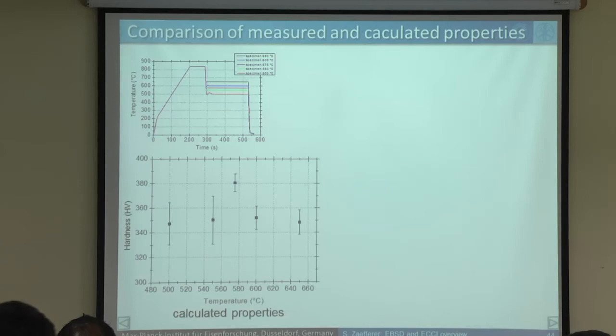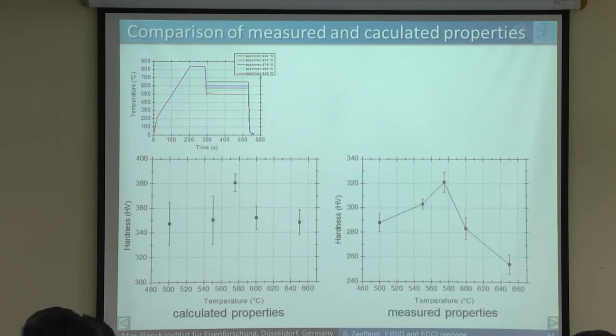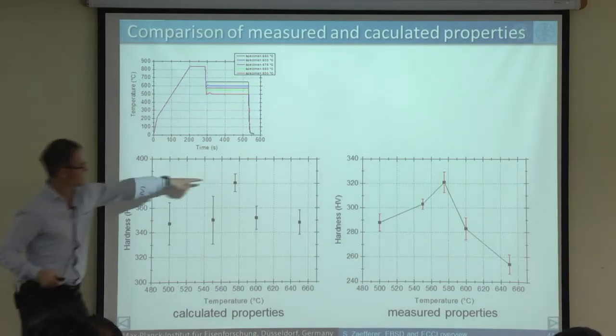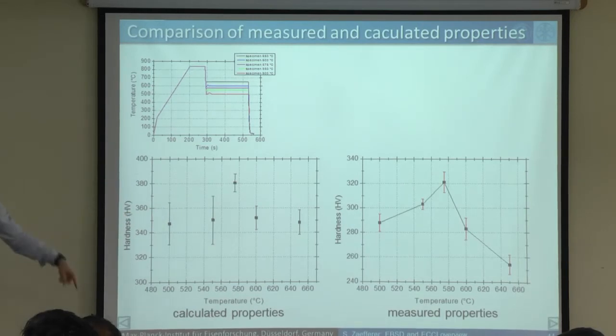And so again, for our experiments, and these are the calculations, and we find out, okay, we do not get exactly, here was our measurement, and we do not yet completely explain our measurements, but we see that the peak is at the same place. We can reproduce the peak. We cannot reproduce the strong decrease of hardening here, and we know why. We are considering only GNDs and not SSDs. EBSD only allows us to measure the GND densities and not the total dislocation density. Therefore, we don't get this drop here, which would be a drop in SSDs, a very significant one. But we can reproduce this.